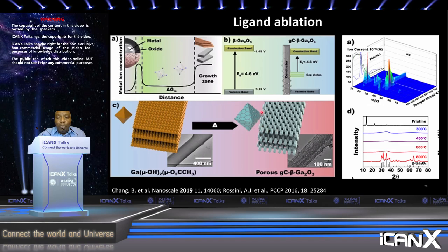which will mean that you will end up having graphitic carbon sitting on gallium oxide crystallites. Gallium oxide is a high bandgap material. It has a bandgap of 4.6. But when you do something like that, you anticipate that this bandgap is going to be much smaller, which allows you to start doing things with gallium oxide that you could never do before. And we call this graphitic carbon coated beta gallium oxide.